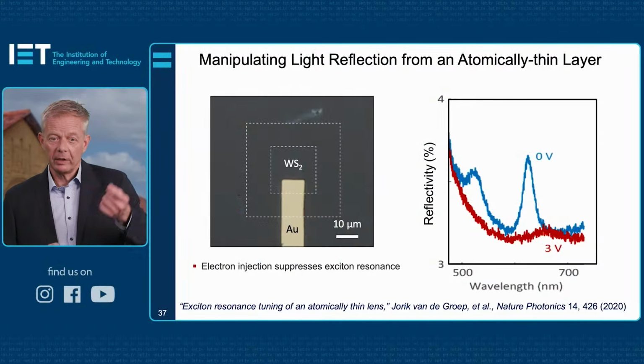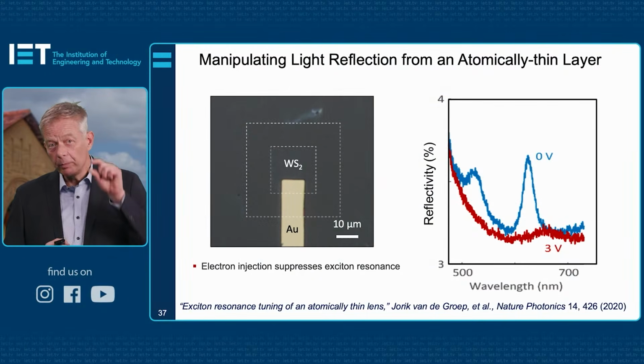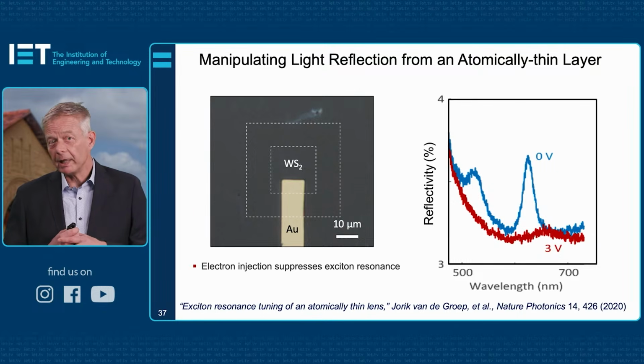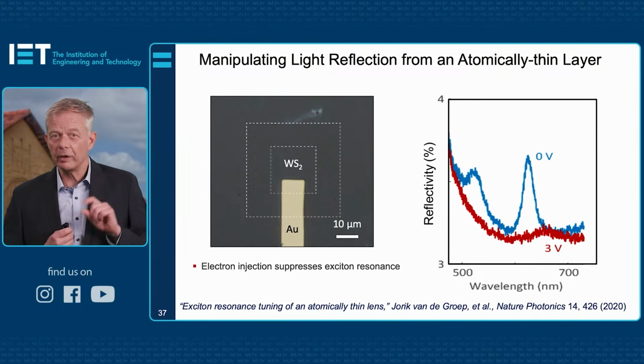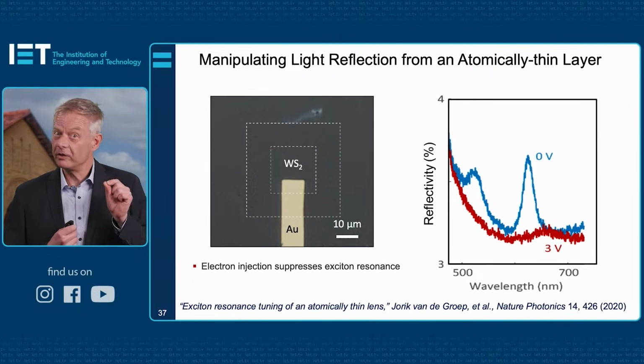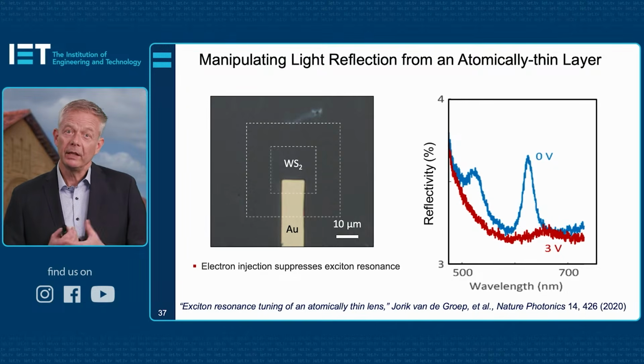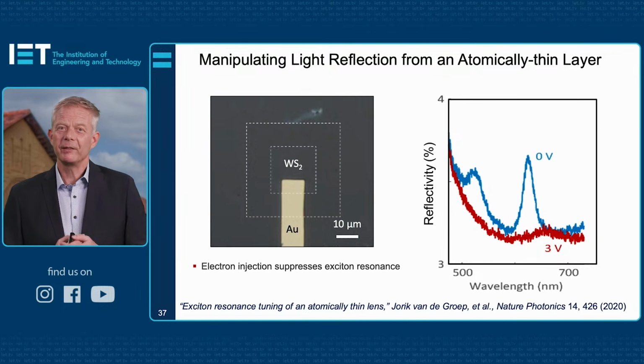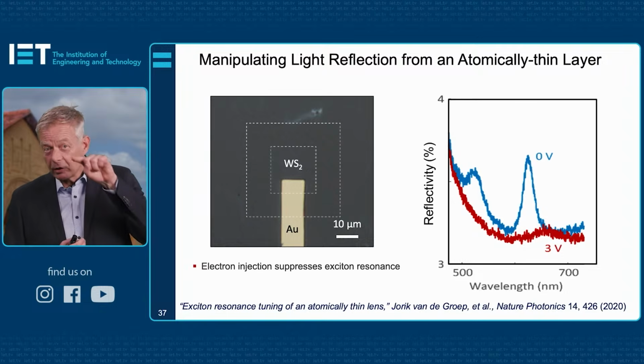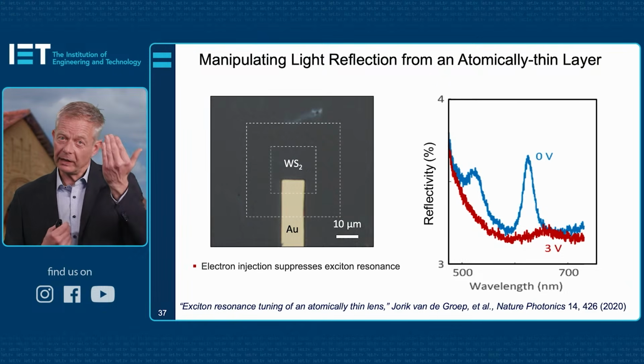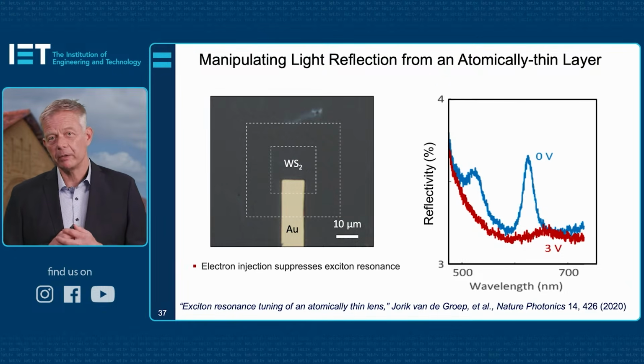This set us off, and this is work by Jorik van de Groep, to make a tiny little island of tungsten disulfide, one of these atomically thin semiconductors. I've outlined it here with a dashed line because it's hard to see such a thin film in visible white light reflection. This is at room temperature. At 4 Kelvin, maybe it would have been more reflective. There's a little trench around it, and we can shine light and take a reflection measurement.